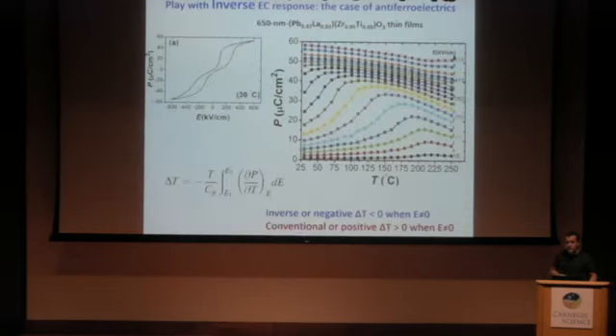What we can do, this is the negative part. Actually, when I say negative electrocaloric, the people from magnetism, they don't like it. Negative means negative, you know, it's not good. And then they used to say inverse, okay? In the sense that once you apply the electric field, instead of having an increase of the temperature, you have a decrease of the temperature. So it's not negative, it's rather good, as Andrew stressed it, yeah? So what we did here, we took an antiferroelectric system, very nice double hysteresis loop, and we applied the electric field, of course, to measure this polarization.